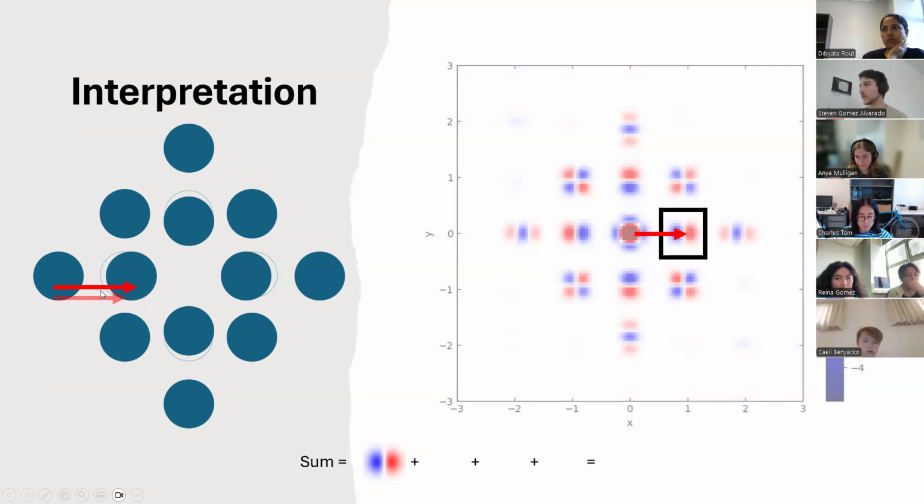Okay. So that is going to contribute on this vector, it's going to contribute something that looks like this, right? There's going to be a decrease followed by an increase. So effectively, the peak is moving to the right in the PDF. Yeah? Okay. So that's not the only thing that's contributing here, even though it looks the same.